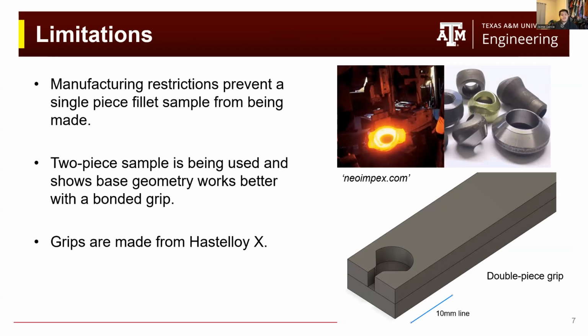We intend to reach 900 degrees Celsius and work our way up to 1200 degrees Celsius. So we will use Hastelloy X for the grips due to its high temperature strength and oxidation resistance at high temperatures, such as 900 degrees Celsius.